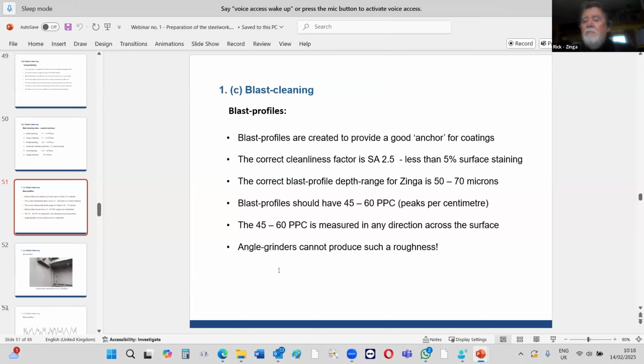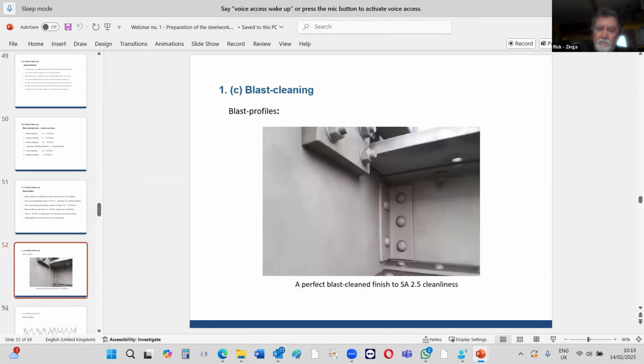You can't see this because it's a little stylus machine, but when they're checking things in a laboratory, checking the abrasive effect on steel, you should have 45 to 60 ppc. When you measure your blast profile, you get peaks and valleys. So there should be a minimum of 45, maximum 60 peaks per centimeter, linear. And that makes sure that the opening is nice. If you had 80 peaks per centimeter, it would be closed, and the paint wouldn't get down to the bottom. So this is ideal. This is why they specify this.